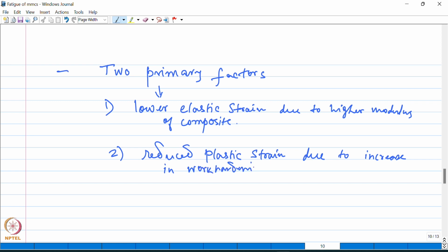We have already talked about this before, as to how the work hardening in the composite is higher compared to that in the unreinforced metallic matrix. So in stress controlled fatigue, these are the two primary factors responsible for higher fatigue life in the metal matrix composite. So you can see that the superior fatigue resistance of the composite basically results from the lower total strain, but more importantly, the lower plastic strain at which it is cycled. Okay.